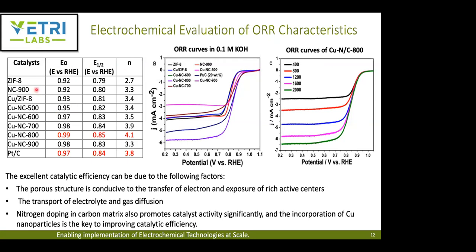So they started with ZIF-8, and then, without any copper doping, they annealed it at 900 degrees Celsius, right? And then doped with copper ZIF-8, and they did it at 5 different temperatures. And they found that the temperature of about 800 degrees Celsius gives the optimal parameter for achieving the optimum balance between this copper-to-nitrogen bond and also the copper-0 nanoparticles.